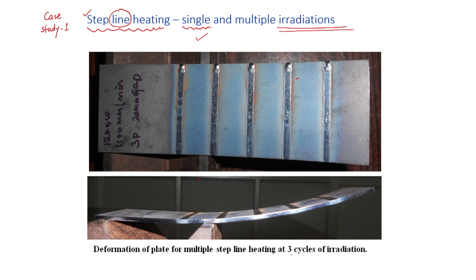Now when we increase the cycles, the number of irradiations on the same line, for all the steps to 3, so 1 to 3 is the enhancement, and you just look at the shape that we are getting. Now the sheet has been bent in a very non-linear fashion, and that may lead to some sort of complex, curvilinear shape that we can give to a very thick plate. You just notice the thickness is significant, and the material is steel. It is particularly mild steel, which has sufficient strength. And that material we are bending by using lasers without any contact of a mechanical tool.